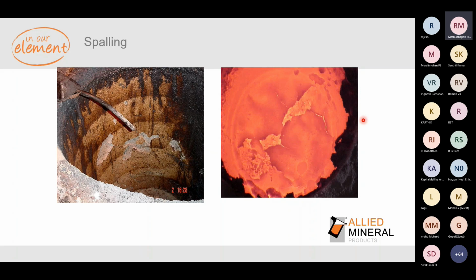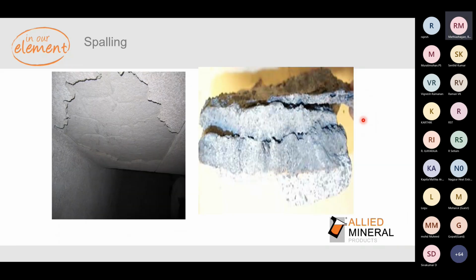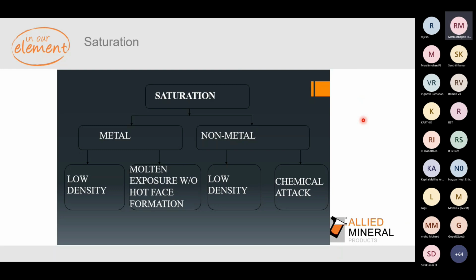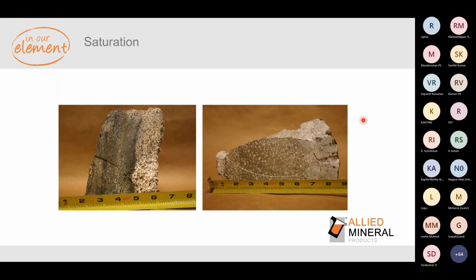So these are some pictures which show spalling. In this picture you can see during the rapid cooling operations they pointed the air towards the working lining, and because of sudden temperature differences, the spalling happens. And here you can see a pin spalling at the bottom. These are steam spallings, which happen majorly in furnaces like channel furnaces or pressure pours or condensers. Saturation, which we already discussed, is because of low density and molten metal exposure without hot face formation, and chemical attack. And these are pictures of saturation, how a saturated lining looks.